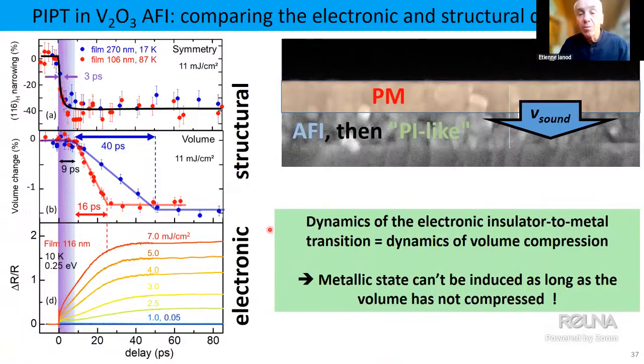And what is even more interesting is that now if I compare this structural evolution that I just showed, in the two upper panels, with the electronic evolution, here I show you the reflectivity as a function of time for the film which is 100 nanometers thick, you see that the dynamics for the reflectivity change, and therefore the dynamics for the electronic change from insulator to metal, is exactly the same as the dynamics for the structural evolution. In fact, it means something quite amazing: the metallic state cannot be induced as long as the volume has not compressed in this V2O3 system.